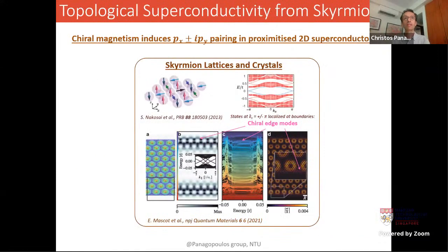Now, theory suggests that spin textures mediated by Dzyaloshinskii-Moriya interaction in a two-dimensional chiral magnet can in fact induce a topological transition to superconducting triplet pairing, that is, an unconventional p-wave superconductor, in a neighboring superconductor which is originally conventional. In fact, a team from Tokyo indicated this back in 2013 using a short wavelength skyrmion lattice.